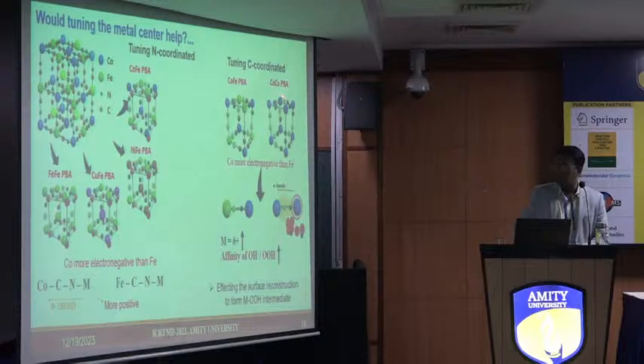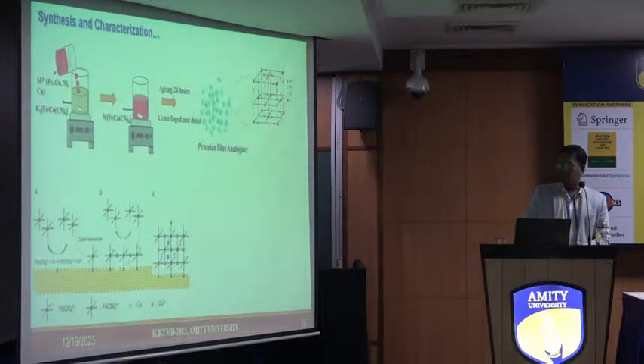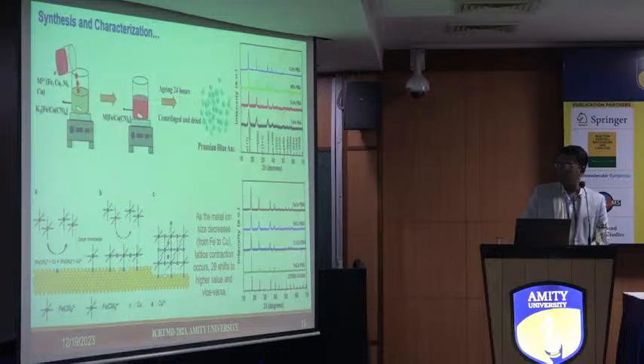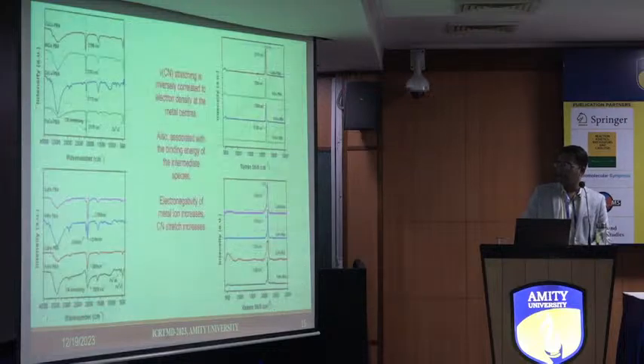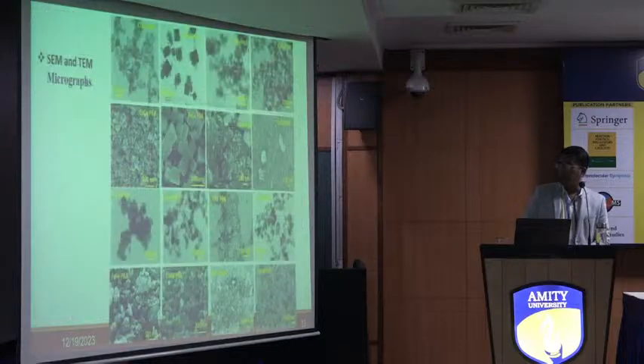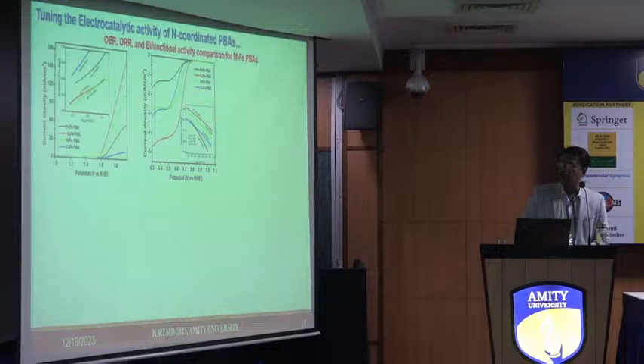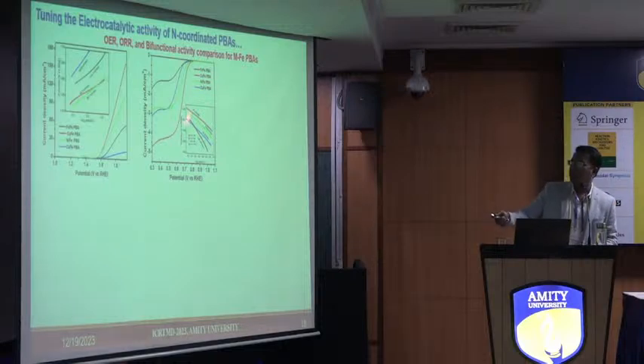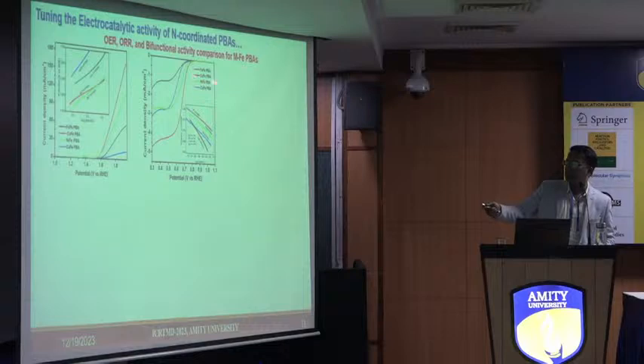And we checked its electrocatalytic activity. Synthesis, I'm not going into the details. We characterized these materials thoroughly using different techniques, including Raman and microscopy. Coming to the electrocatalytic measurements, these are the oxygen evolution reactions. These are the oxygen reduction reactions. What you can notice is that among these catalysts, CoFe PBA is a good catalyst for the oxygen reduction reaction as well as the oxygen evolution reaction.